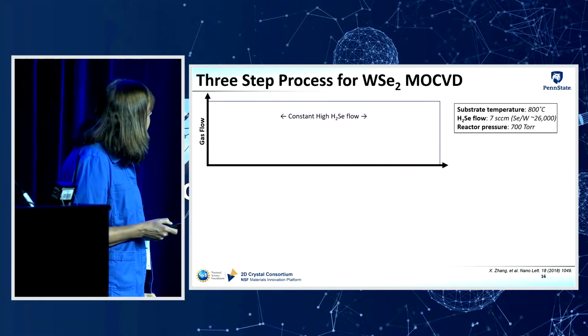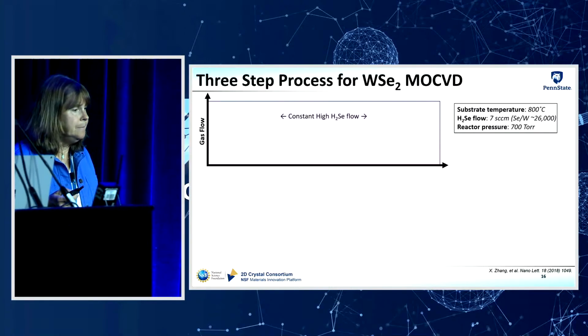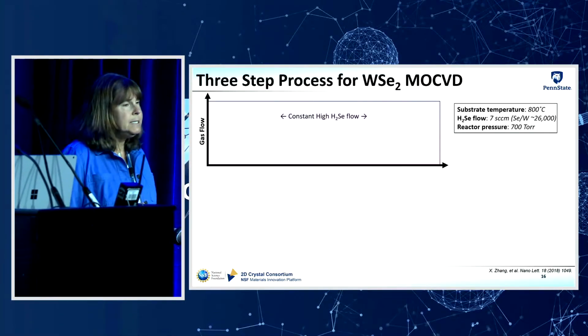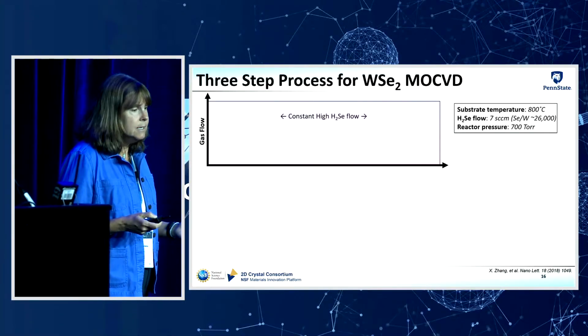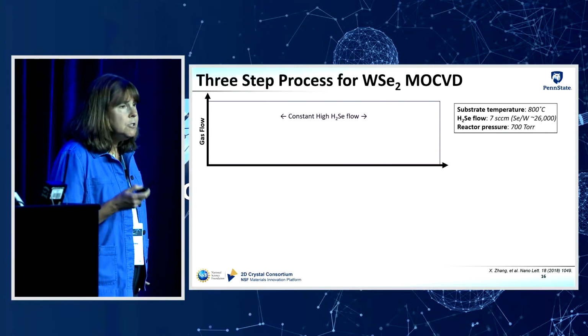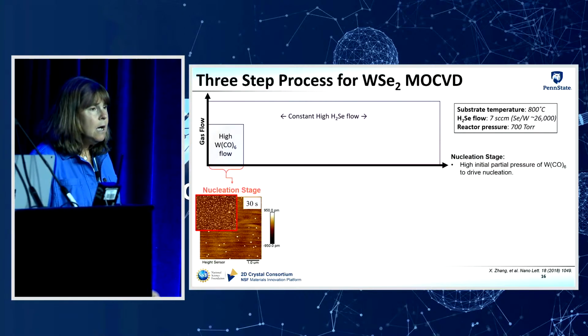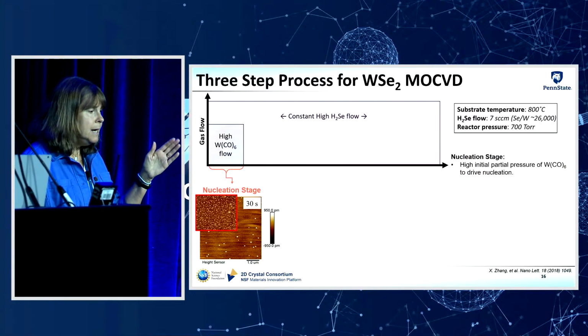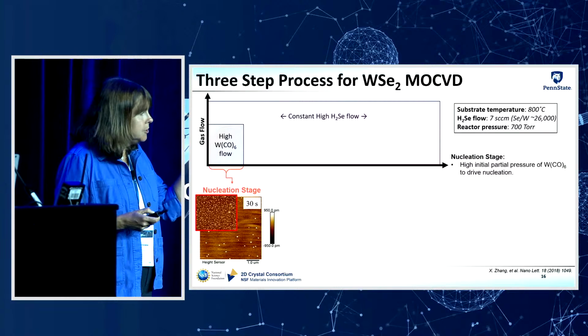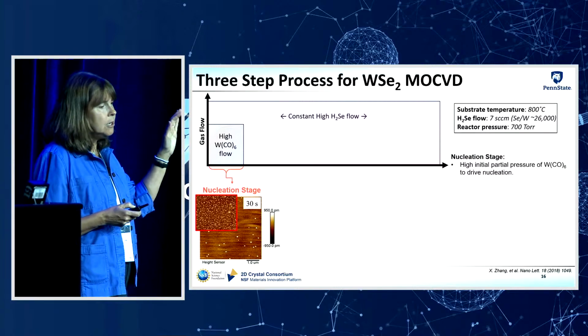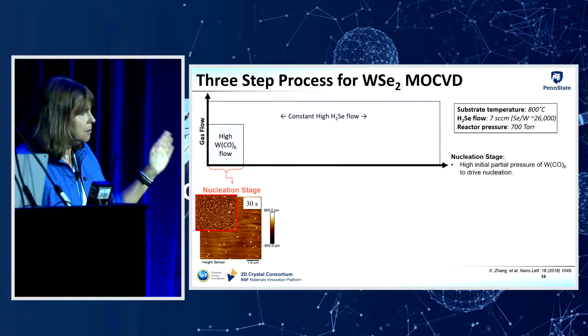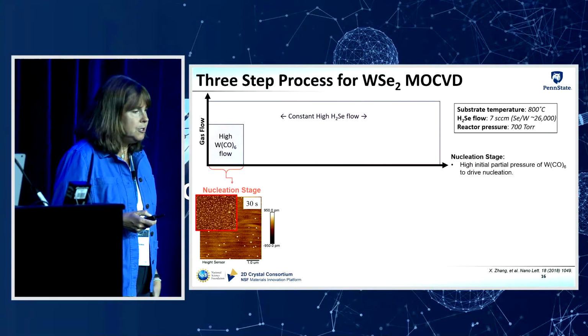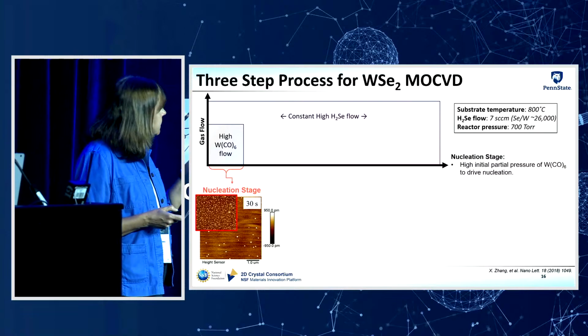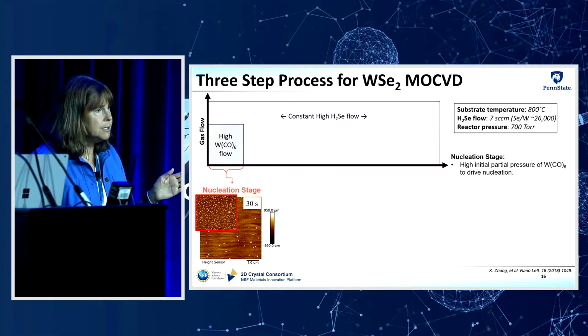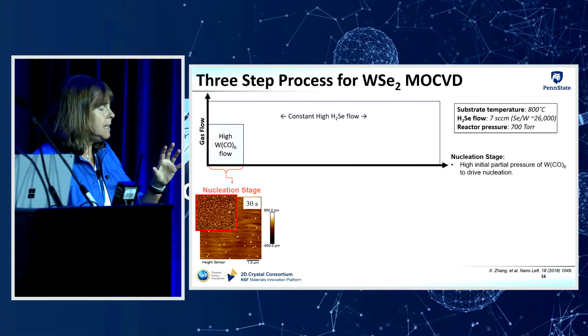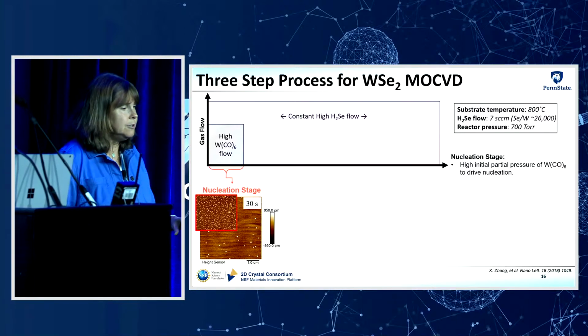So let me tell you a little bit about the process that we use for epitaxy. Specifically, this is an example for tungsten diselenide growth on C-plane sapphire. We developed this three-step process. We start out using a high flow rate of the tungsten source, and I should mention that we're carrying this out under a constant flow of hydrogen selenide. So we always have the selenium, or the chalcogen, present in our growth environment. We initially use a higher flow rate of the tungsten source to help supersaturate the vapor phase and drive nucleation on our substrate surface.